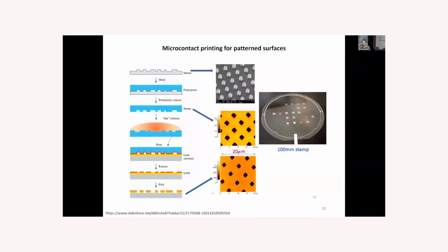So we also work with some patterned surfaces of self-assembled monolayers. And here I wanted to show you how we make the patterned surfaces. So we use the technique of microcontact printing, which is basically creating a master to create the polymer stamp, which then is released from the master and is covered by a solution of the molecule we want to print on the surface. Then we can print it on the gold surface and take out the stamp, and we obtain patterned surfaces of, it can be lines, it can be circles, it can be any form you would like to have to study.